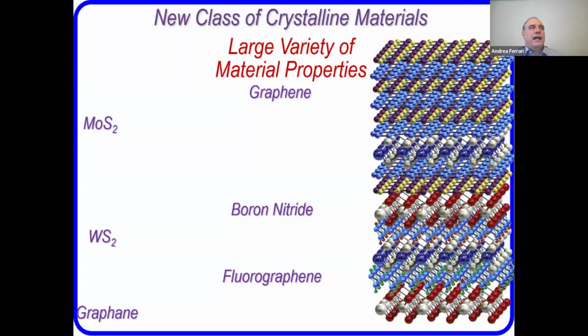And not only does the arrangement of the layers, one with respect to the other, give the properties, but also the relative orientation. For example, let's take graphene, two layers of graphene, one next to each other. If you change the angle, you can go from a metal to a semiconductor, to an insulator, to a superconductor. And in fact, at the magic angle, in 2018, the group of Pablo Jarillo-Herrero at MIT has shown superconductivity properties related to the presence of flat bands. And this has really initiated or spurred a large field of research.